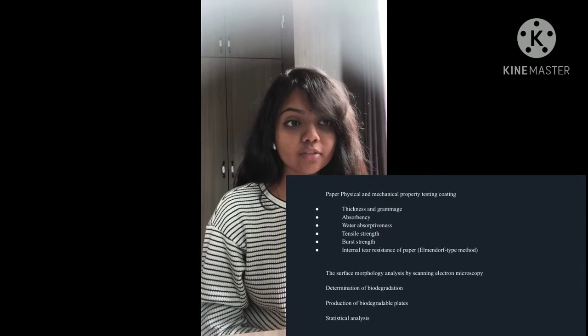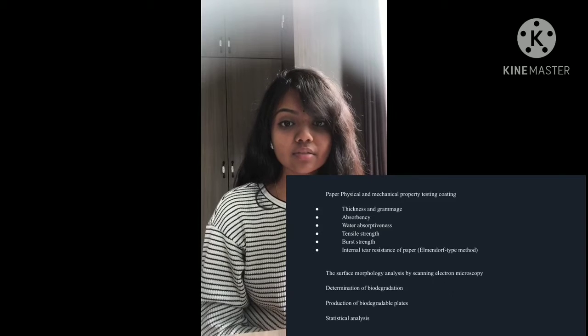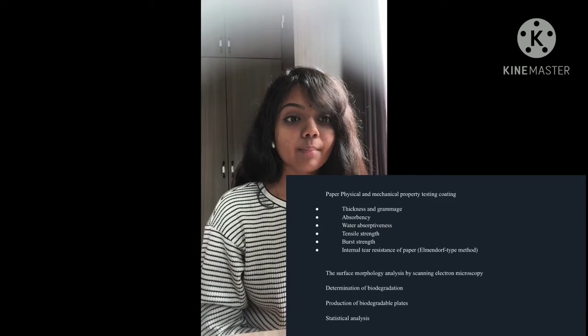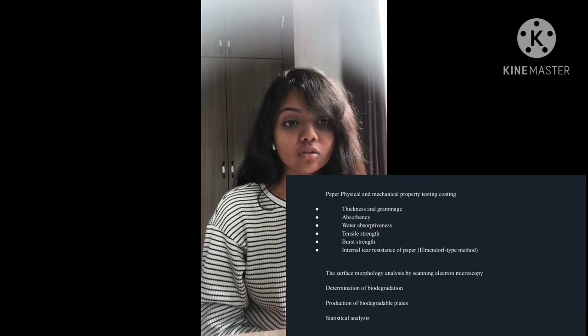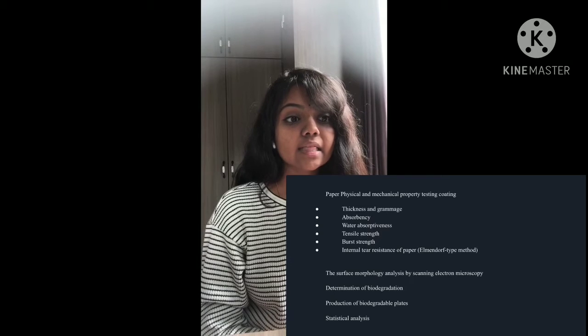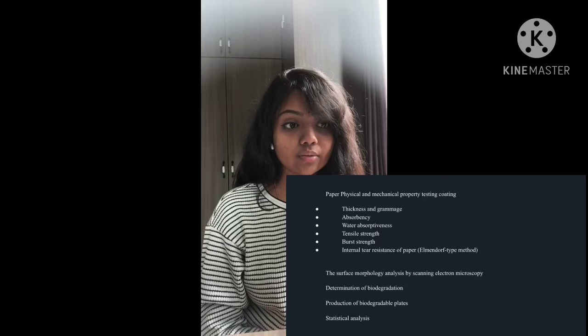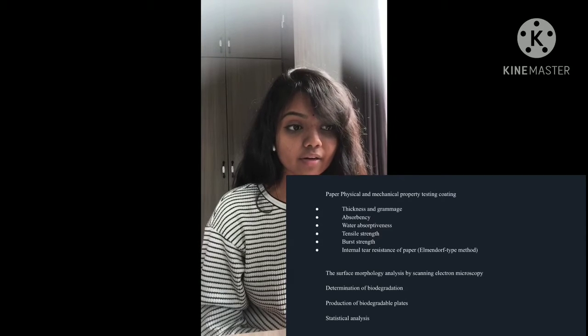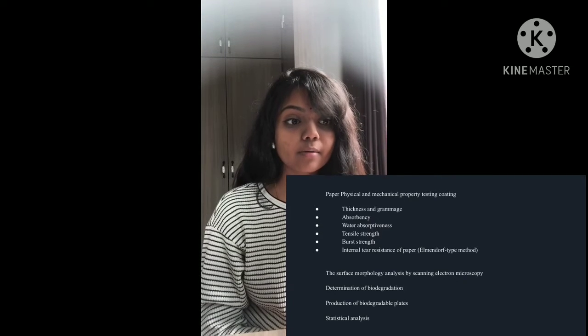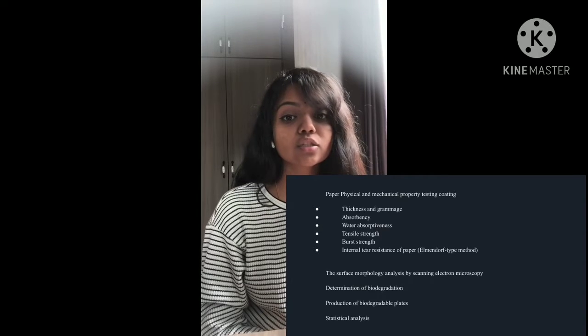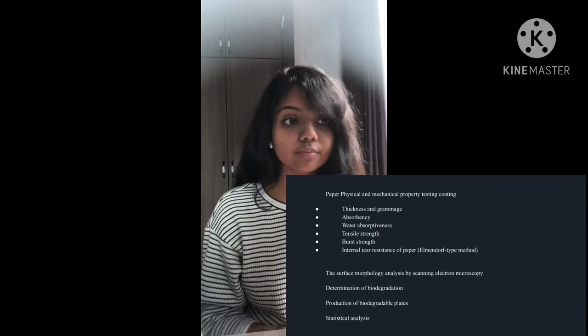the absorbency, the water absorptiveness, the tensile strength, burst strength, and internal tear resistance of the paper. The method used was the Elmendorf type method, and then the surface morphology analysis by scanning electron microscopy was used. The determination of the biodegradation, the production of the biodegradable plates, and the statistical analysis were also carried out.